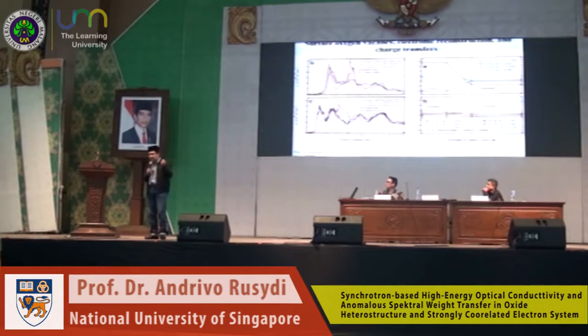Right? So you can precisely tell me, oh, there are 10 electrons there, there are 5 electrons per unit cell, or there are 20 electrons per unit cell. You can tell that so precisely if you identify the spectra properly. Right? Now we do that. We integrate the spectral weight of reflectivity, and then we can find out the origin of the metal for 4 and 6 unit cell of LAO on STO. Okay, so take a look at what happened. It turns out that, again, this is the number of LAO unit cells, and this is the number of electrons per unit cell for individual.